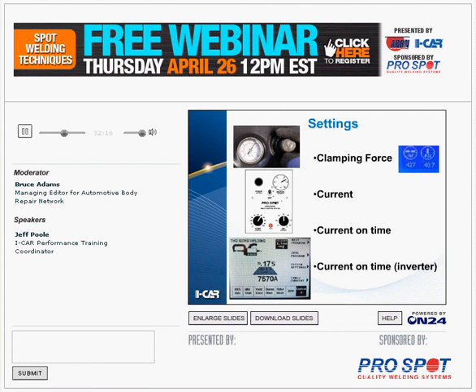There becomes, again, another point of diminishing returns here. Too much heat can be detrimental. And again, this can distort the tips, and in some cases it's actually creating a weaker weld because of the detrimental effects that heat may be having on that metal that we're welding. So a large heat mark around the spot weld can be an indicator that we've had too much time.